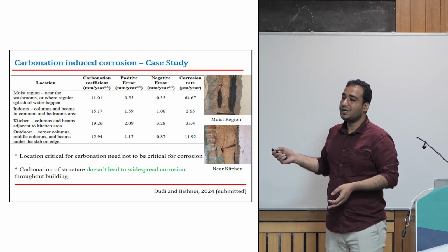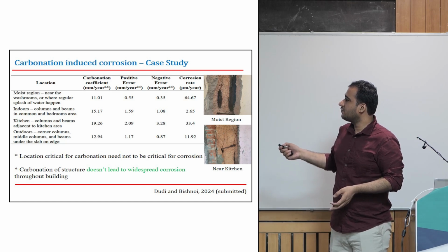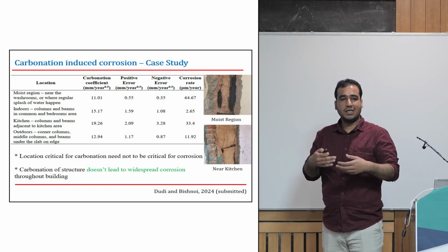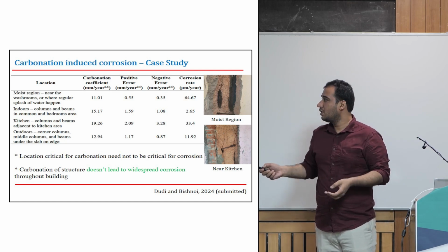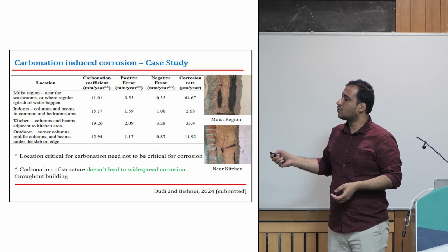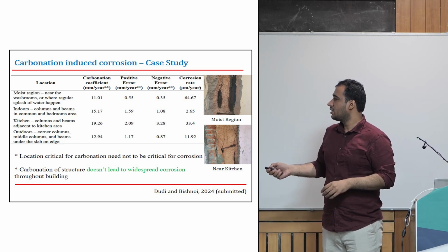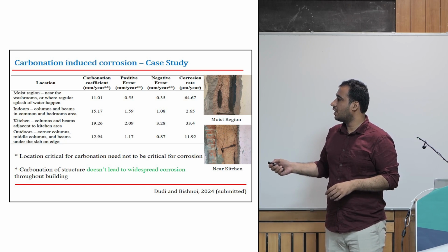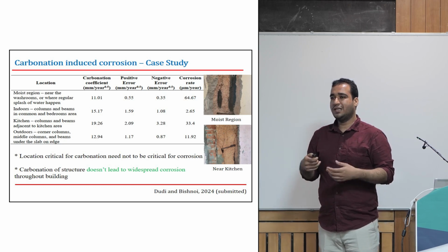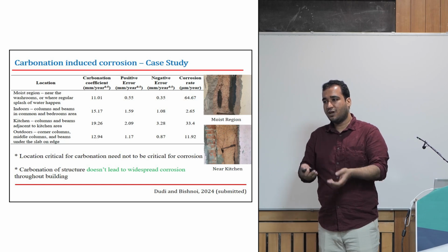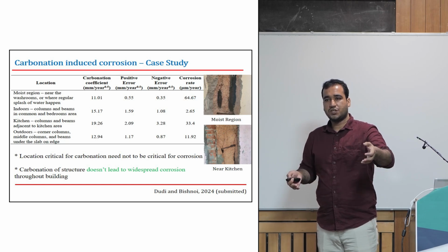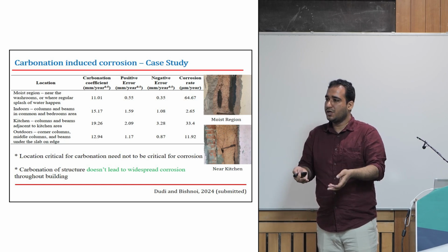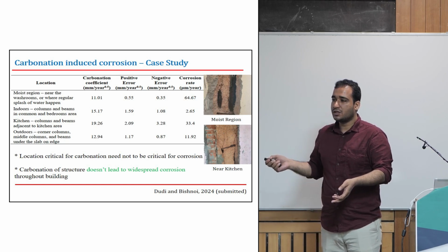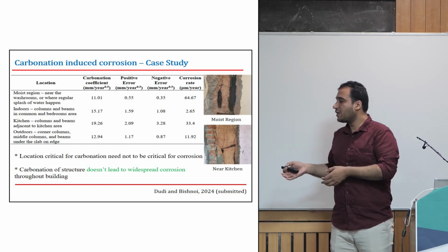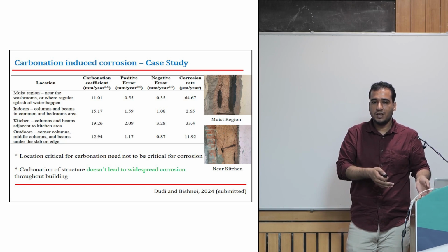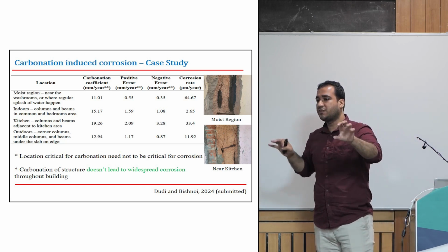You see, micrometer per year. So only the regions which were quite moist and repeatedly being subjected to moisture and water observed quite high corrosion rate values. These regions are specific. Then again, the regions where the carbonation depth was quite high, the corrosion rate was not high. These are indoor environments where we live. We have a low relative humidity, so the carbonation front can move faster. But since we don't have a high relative humidity there, we don't get much of a corrosion rate. So it's not a widespread corrosion in a structure when structures get carbonated. It's more of a location-specific reason.